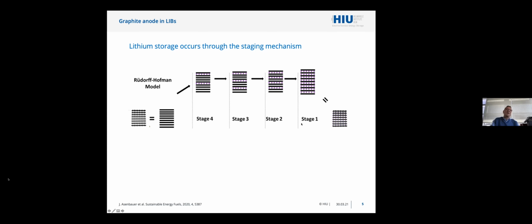And what is actually happening in reality was well described by the model of Daumas and Hérold, in which in practice lithium is more or less entering in all layers, but it's locating in different positions, so that what we see if we are looking only at a small area like this area, we see the same picture as here. But in this way, it is obviously much easier to understand how it can happen that other layers are filled. Don't forget, never forget, the lithium can never go across the layer. It can only enter from the edge and migrate inside.